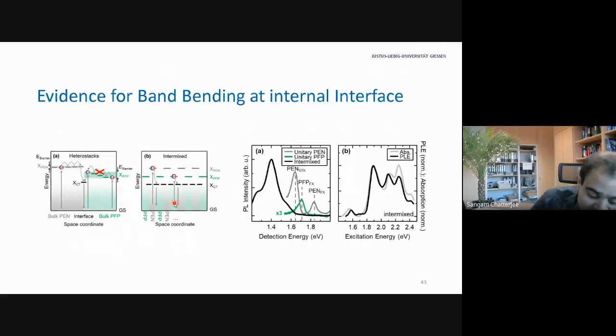What is happening here is a coupling effect between the molecules, in particular in the PFP. As we found out, this PFP actually couples. And when you do a calculation where you basically start with a dimeric picture, so you calculate one pentacene and one PFP, you get the energy, the orbitals at the interface. And then you expand your calculations by adding two pentacenes and two PFP, and you can find the energy positions of each of those. And then you can go one step further.